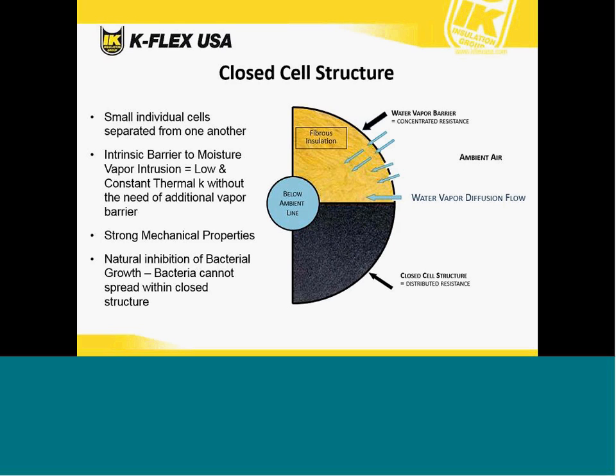So it gives us a water permeability for our products. Well, that's from our closed cell structure of elastomeric insulations. What this means is there are small individual cells with a physical barrier that are separated from one another. That gives us an intrinsic barrier to moisture vapor intrusion, a low and constant thermal K without the need of an additional vapor barrier. Also strong mechanical properties, they're physically bonded to each other, and natural inhibitor of bacterial growth.